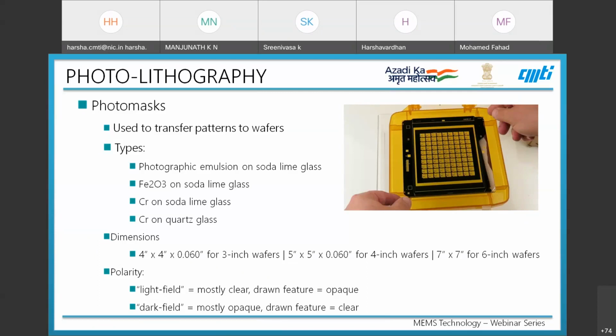Generally these masks are available in different sizes: about 4 inch by 4 inch for 3 inch wafers, 5 inch by 5 inch for 4 inch wafers, and 7 by 7 for 6 inch wafers. The wafer size will be 1 inch smaller as compared to the photo mask used for the transfer application.